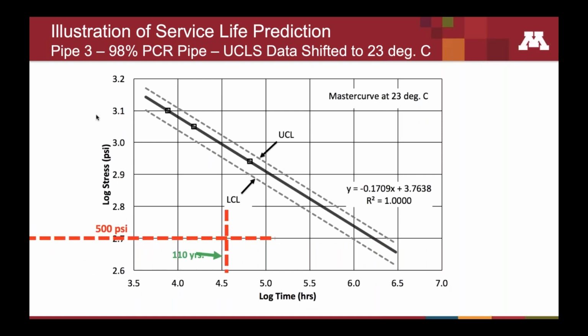If we looked at a pipe with 98% post-consumer recycled materials, we could see that that pipe would also last in excess of 110 years at a service stress of 500 psi and a service temperature of 23 degrees C. So this is encouraging. This is exciting. We felt that we had something workable here.